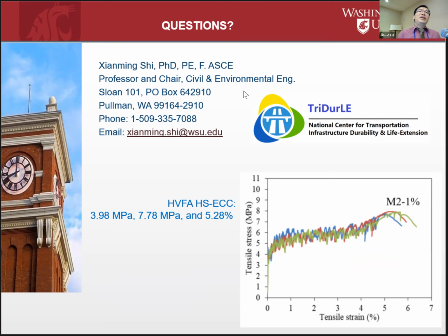Right. Yeah. In this case, we use the Class C fly ash, which, I would say, Class C in the country probably is about 15% of the ash out there. More commonly people use Class F. However, there's a benefit of using Class C because Class C traditionally is really difficult to use. So if we find a good outlet for it, it's nice.